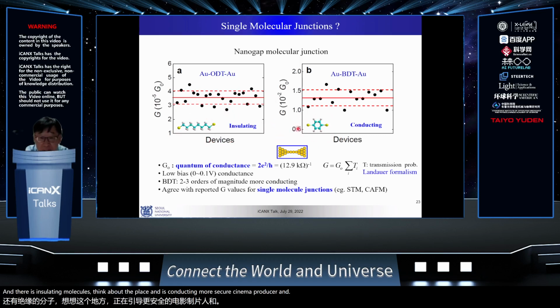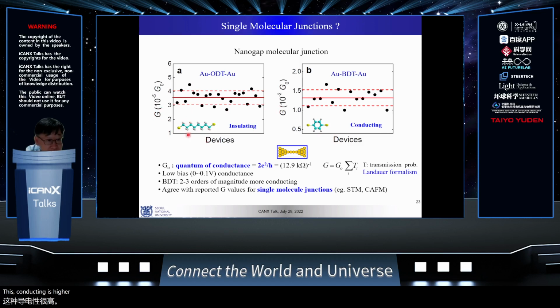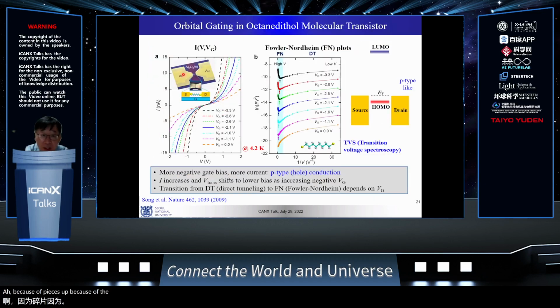And the conductivity of this conducting one is higher than this one by a factor of about 100. So you can see the conductivity 0.01 times something, 10 to the minus 5 times something. This G0 is the one-dimensional quantum of conductance, known as this value. Okay. So the yield is poor because of the electromigration.